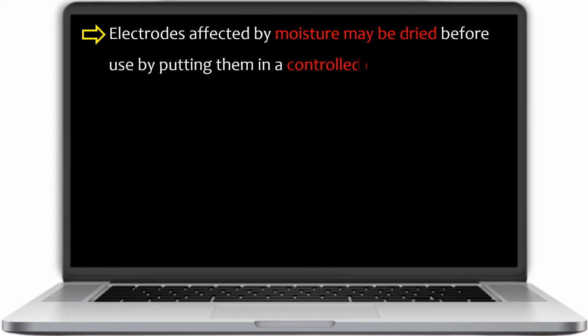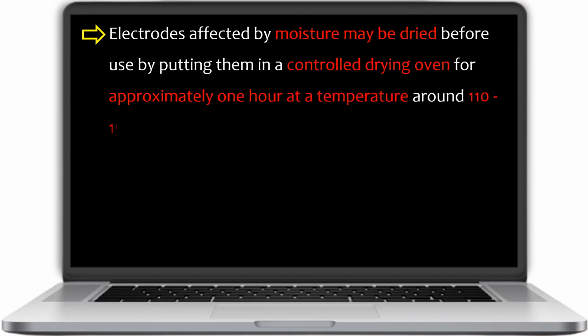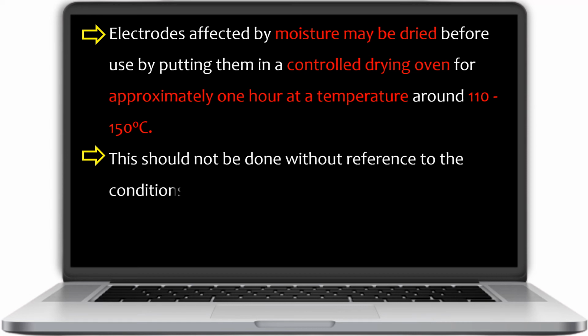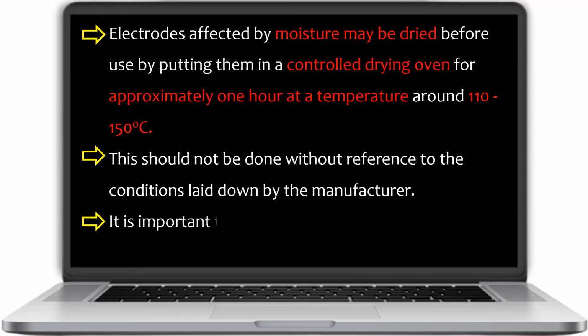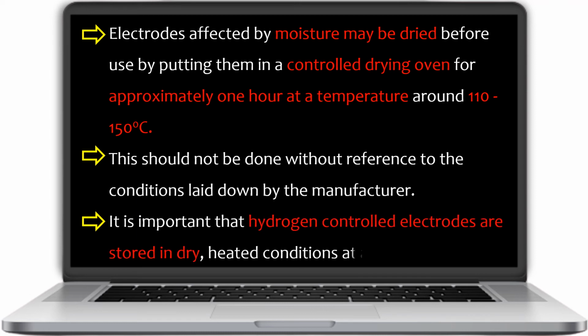Electrodes affected by moisture may be dried before use, by putting them in a controlled drying oven for approximately 1 hour, at a temperature around 110 to 150 degrees Celsius. This should not be done without reference to the conditions laid down by the manufacturer. It is important that hydrogen-controlled electrodes are stored in dry, heated conditions at all times.